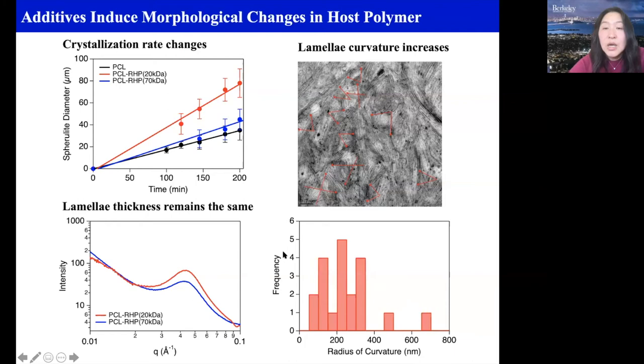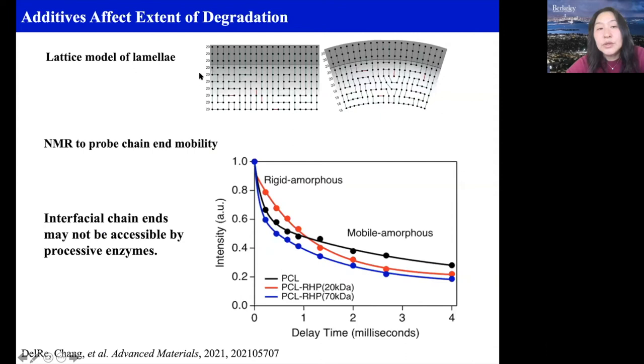If you go back and look at a very simple lattice model of the lamellae, and you want to see how your polymer chain is going to arrange, it turned out that if you go from a flat lamellae to a highly curved lamellae, you are going to change the accessibility or the spatial distribution of your polymer chain ends. The polymer chain end is readily sequestered at the interface because it's the best way to release the cross-sectional mismatch, to release that curvature, to stabilize that curvature. And once the polymer chain end is sandwiched at this interface, it's not accessible by the enzyme anymore.